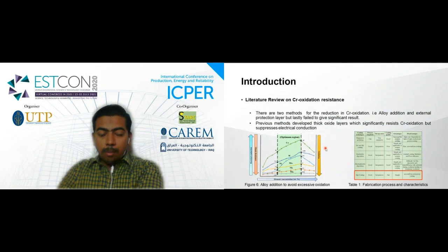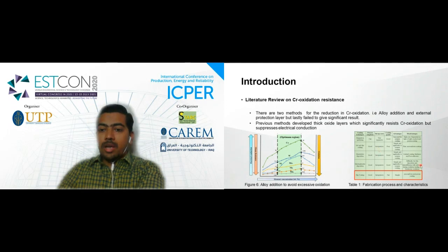From previous research works, we concluded that different types of alloying elements have been added, and it increases electrical conduction and decreases oxidation, but not significantly, so we cannot use it widely. So here we have another method of controlling chromium migration. This is a coating technique that has been used by different researchers with different spinel layers, but none of them worked significantly. I use dip coating because it is an easier method. I decided to coat a layer over this surface. I will discuss this later.